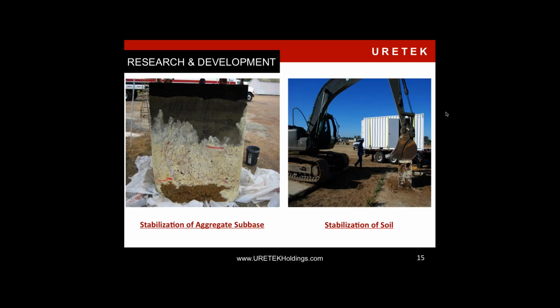On the research and development side, the picture on the left shows an asphalt surface on top, then your base materials, then your sub-base. High-density polyurethane was injected into this area. As it permeates through the soils, it will blend with the soils. It will expand in the path of least resistance. It does not displace the soils or aggregates and create a big ball of foam, if you will. It will permeate and blend with those, not only increasing the load-bearing capacity, but also the tensile strength.